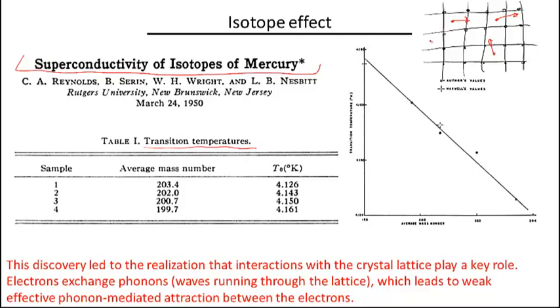So what it turned out, and this is really the main message of the paper, that the transition temperature into the superconductor, the temperature at which the resistivity drops exactly to zero, depended very strongly on the mass of these guys. And the heavier the ions, the lower was the transition temperature. So this is Tc, and this is the mass of these ions on lattice sites. This was a very clear cut trend, and it was a smoking gun that superconductivity had something to do with interactions between the electrons and the crystal lattice.